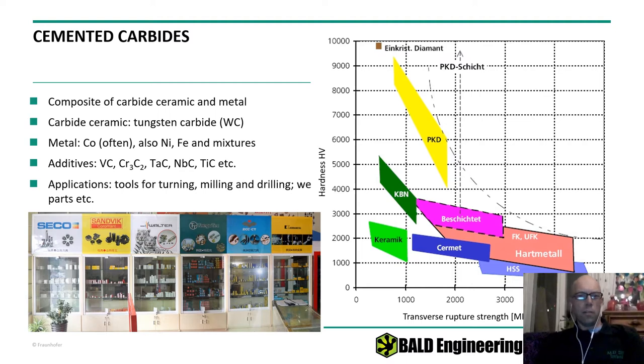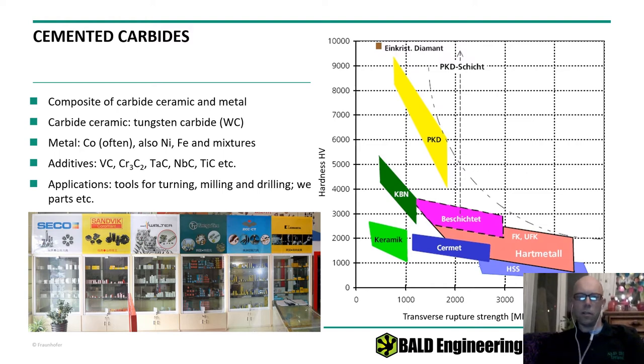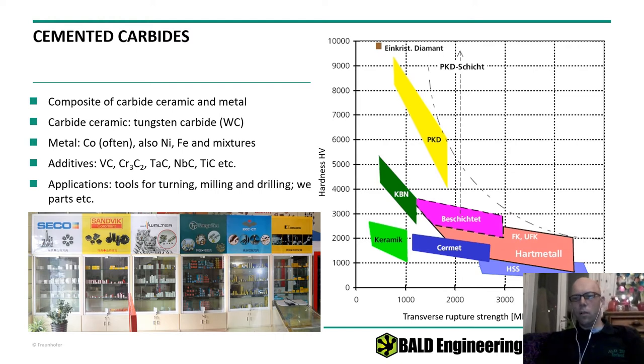What you do is put in cobalt as a promoter before the sintering process to act as a glue between the grains that stick together. We are trying to control this process in more detail. There's a whole range of other additives — chromium-based carbide, tantalum carbide, niobium carbide, titanium carbide.